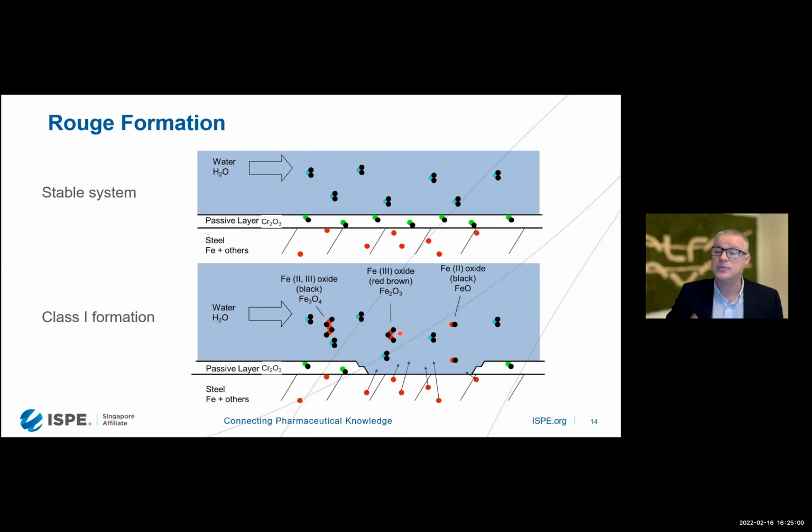And when it comes to turbulent areas, it will be smashed onto the surface and get deposited on the surface. It is also that plastic materials, PTFE in the diaphragm, EPDM in the diaphragm or in the gaskets, will also, nearly like a magnet, suck in this iron oxide onto the surface.